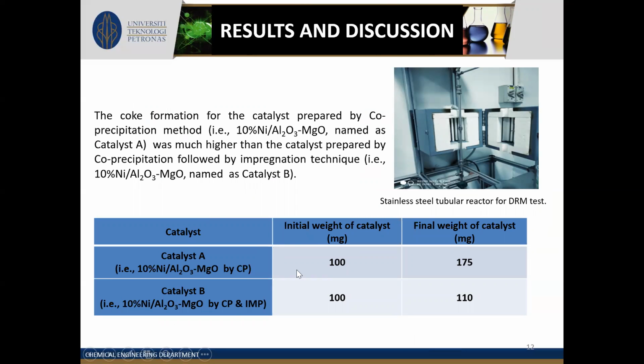In the reactor, we took 100 milligram of the catalyst, and then we did the dry reforming reaction for 6 hours and weighed the final catalyst. We can see that 75 milligram of coke has been formed for catalyst A, that is the single-step synthesis catalyst, and only 10 milligram of coke has been formed for catalyst B, which is prepared by co-precipitation followed by impregnation.